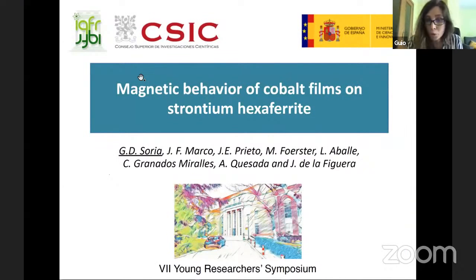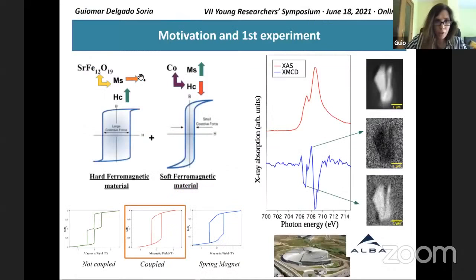Okay, hello to everyone. My name is Guiomar Delgado Soria, and I'm going to introduce my work called Magnetic Behavior of Cobalt Films on Strontium Ferrite. First of all, the motivation is that we are looking for an alternative to the current permanent magnets, and a good material for this is strontium ferrite. Why? Because it has many promising magnetic properties like high magnetocrystalline anisotropy, elevated Curie temperature, good wear resistance, and most importantly, a high coercive field.